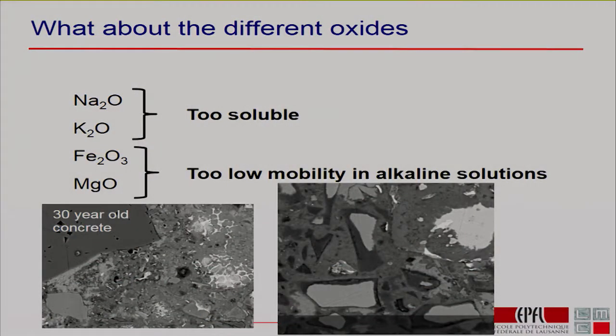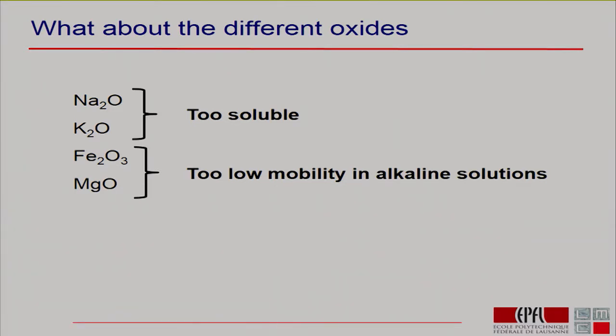This is a picture of a slag cement, a blend of slag and Portland cement. And these grains here are the slag grains, and they've partly reacted. Where they've partly reacted, you can see they've got these dark zones, and the reason is that's where all the magnesium is. Slag contains magnesium, and the magnesium in that slag just stays where it originally was. So it doesn't go into the space here. It doesn't bridge the spaces between the grains. It doesn't contribute to the strength development.